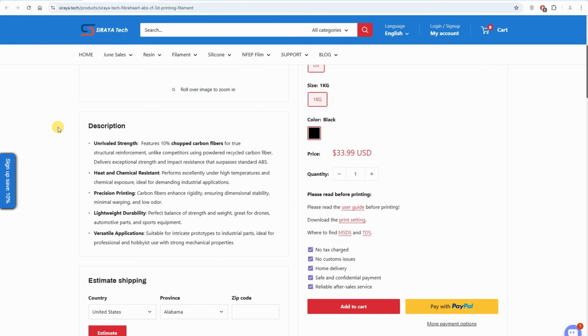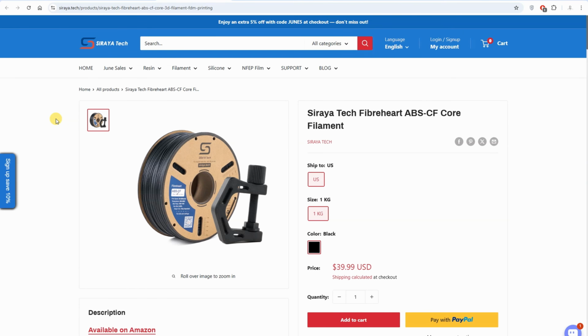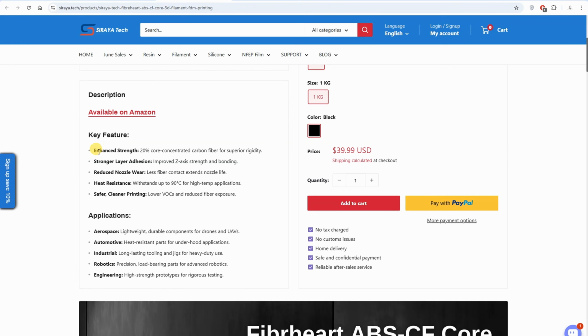Now let's see some specifications. About ABS-CF: it contains 10% chopped carbon fibers, it is a heat and chemical resistant material, and it has dimensional accuracy and great rigidity. And now about the core version. It contains 20% core concentrated carbon fibers, and with this we have all those advantages of the core filaments, like a stronger layer adhesion, reduced nozzle wear, safer because fiber exposure is reduced, and we have a smoother surface. It is heat resistant and it can be used up to 90 degrees Celsius applications.